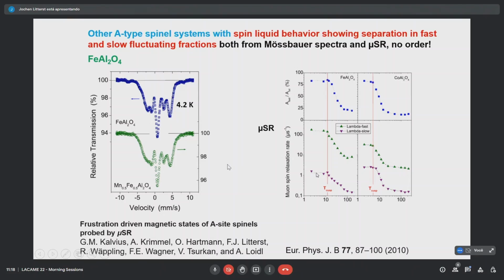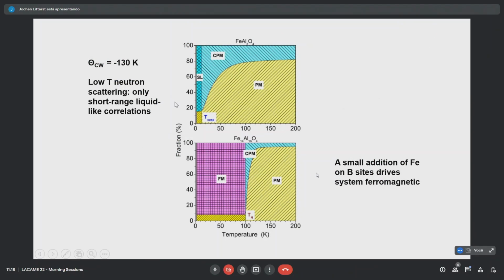From the muon side, we can see that down to 25 millikelvin, for sure not with the Mössbauer part, and that's indicating we are in a kind of spin liquid state. Here comes the neutron data also, which are consistent with our data: high temperature paramagnetic, what is called cooperative paramagnetic, strongly correlated paramagnetic state, and below about 20 Kelvin, or no, 15 Kelvin, we switch over to a dominantly spin liquid phase and a kind of spin glassy phase.